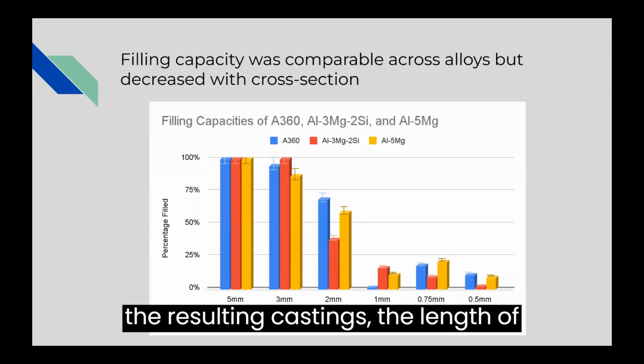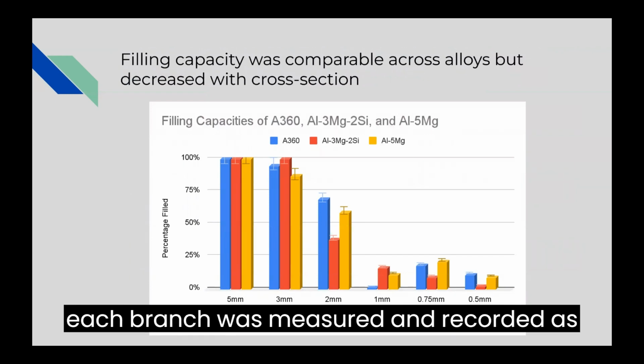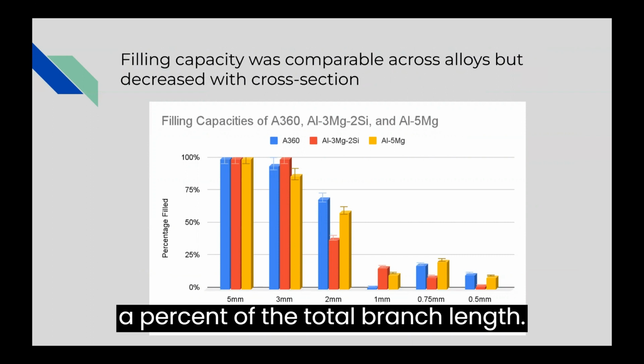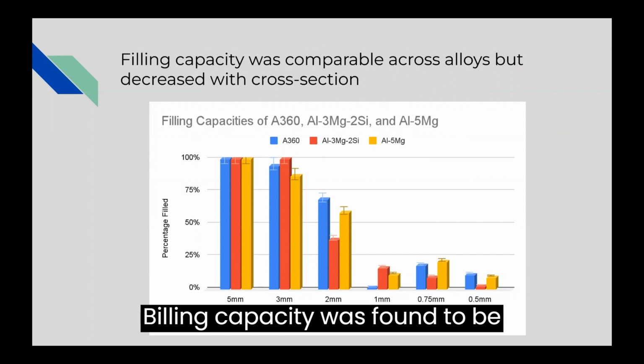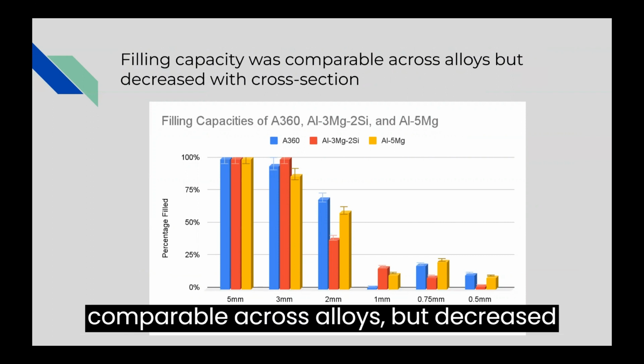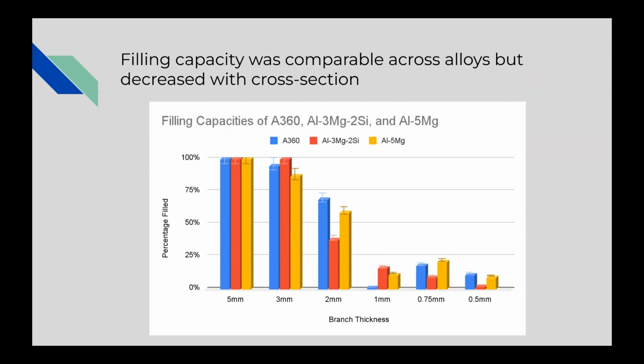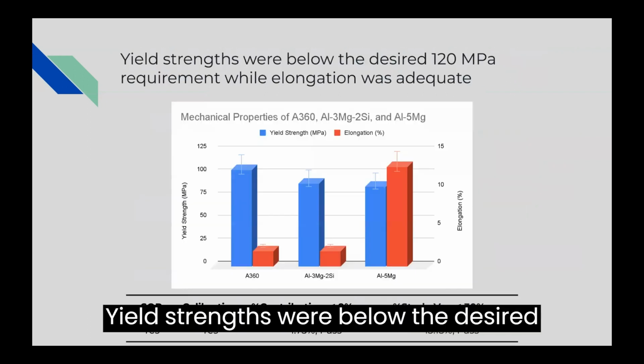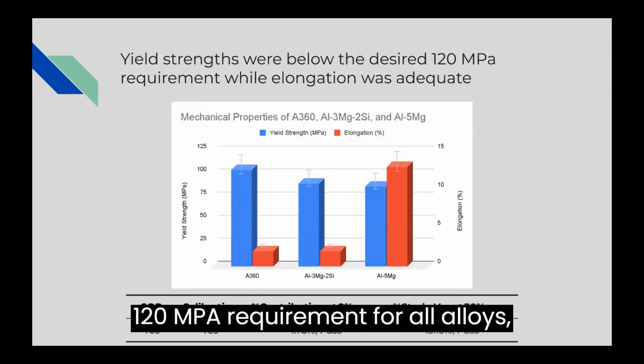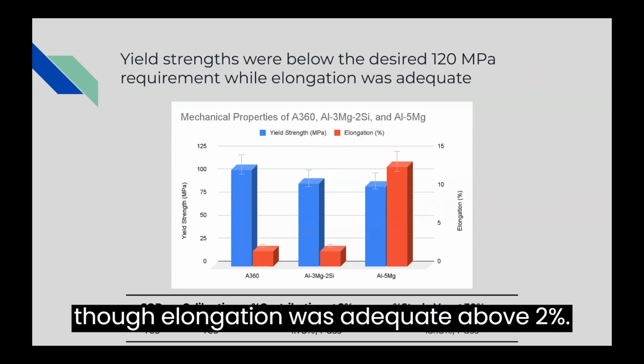From the resulting castings, the length of each branch was measured and recorded as a percent of the total branch length. Filling capacity was found to be comparable across alloys, but decreased with cross-section. Yield strengths were below the desired 120 MPa requirement for all alloys, though elongation was adequate, above 2%.